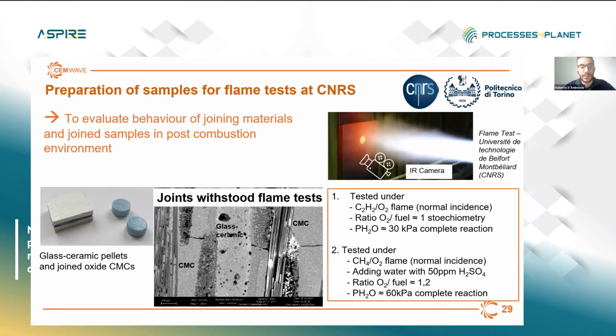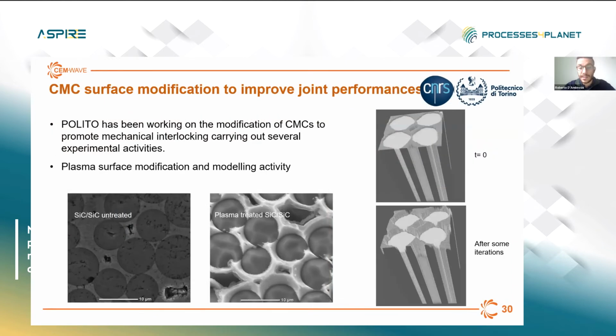Furthermore, as for the oxide-oxide joining material candidates, they've been also validated in post-combustion environment, thus simulating the real operating conditions in two different sets of parameters, which are depicted in the orange box below. As you can see, the joints withstood quite well the flame tests with no mass and microstructure evolution during the process. Another important complementary activity regarding the surface modification of the CMCs, since we wanted also to further improve the joint strength by favoring a mechanical interlocking of the joining materials with the underlying CMC substrate. And this activity has been also flanked by numerical modeling activities.